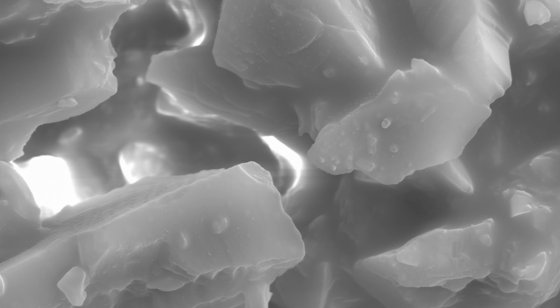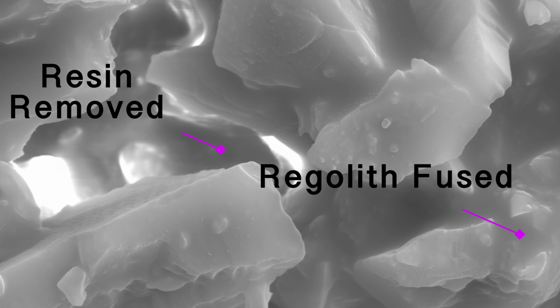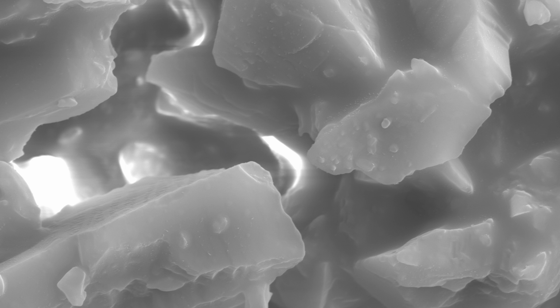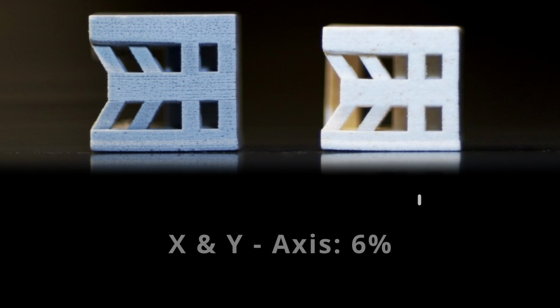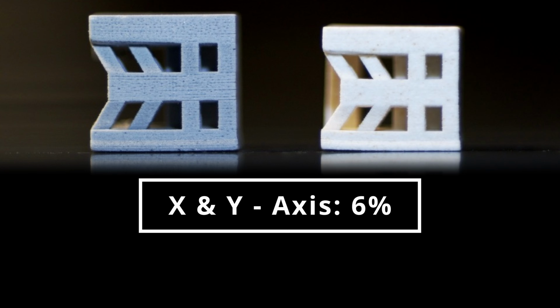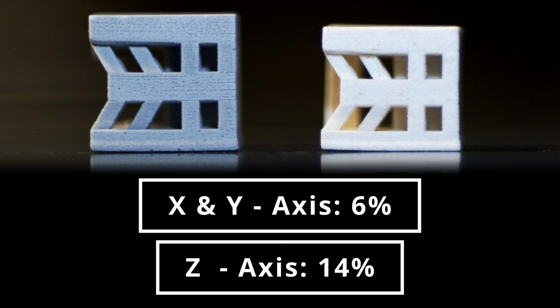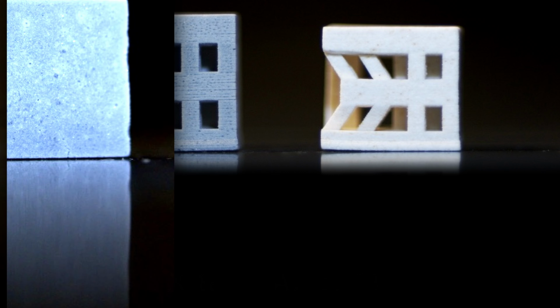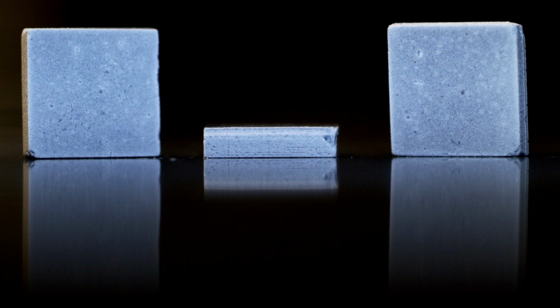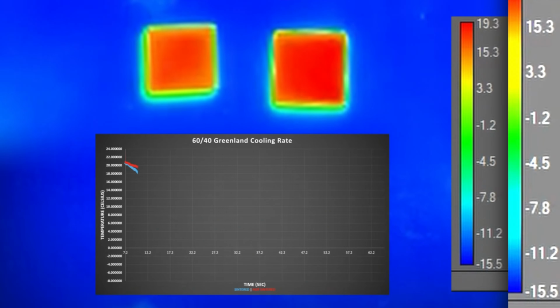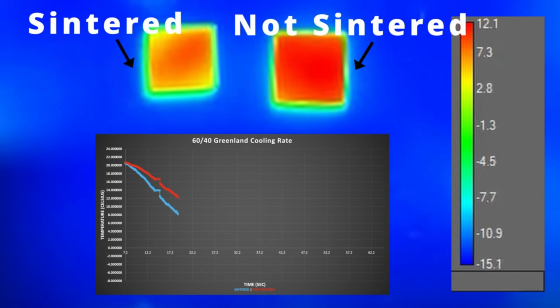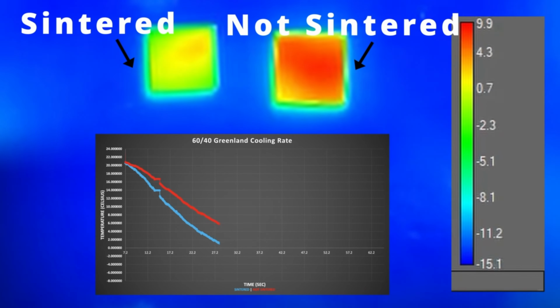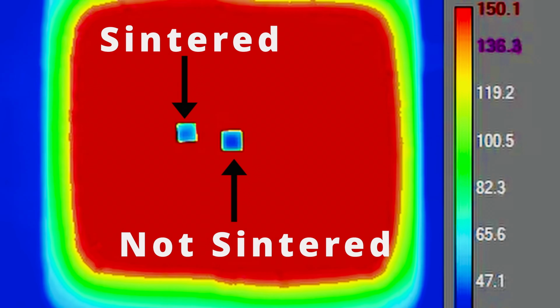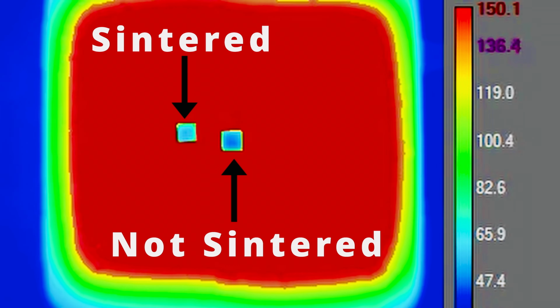The removal of the resin does leave some porosity in the part, and the goal is to reduce the porosity as much as possible by loading the slurry with regolith at as high of a concentration as possible. There's shrinkage of around 6% in the X and Y direction, and gravity causes the part to shrink 14% in the Z direction. We also printed samples for thermal testing. The sintered sample cools quicker than the printed non-sintered sample. And the sintered sample also heats up quicker than the printed non-sintered sample.